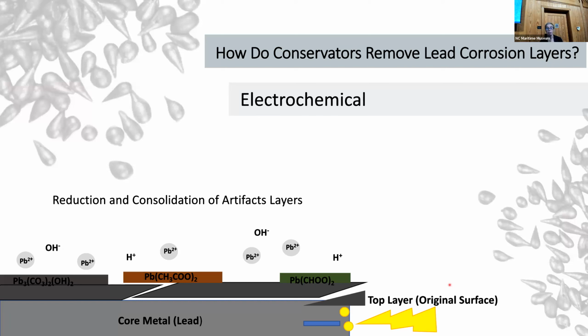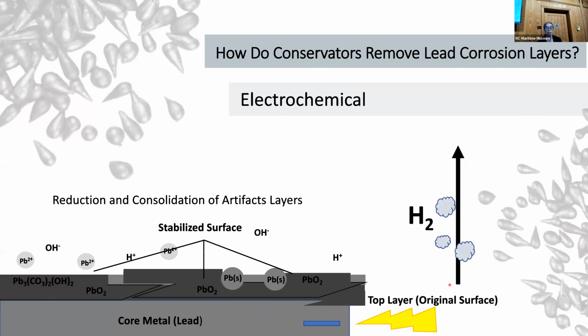We're then adding in electricity. So basically we're feeding electrons into the system, which are then being fed into these ions, which are then essentially turning into stable solid lead, which can fill in these gaps in the surface and deposit on the surface, as well as more stable corrosion products, which is helping to consolidate or stabilize the surface so we don't lose it, and it's turning into something that is more favorable to the environment that it is in. It's also producing hydrogen gas, which can basically pop off anything on the surface that we don't really want there that's very lightly adhered, like the corrosion products, etc.